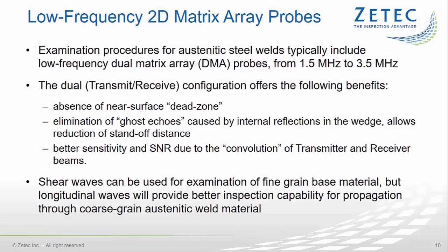Examination procedures for austenitic steel welds typically include low-frequency dual matrix array probes, often called DMA probes, with frequencies from 1.5 to 3.5 MHz. The dual transmit-receive configuration offers the following benefits. First of all, there is no near-surface dead zone. Also, there are no ghost echoes caused by internal reflections in the wedge. This means that the wedges don't require any dampening material on the front, so they can be made shorter. And as a result, the exit point of the probe can be positioned closer to the weld. This will allow for better coverage in the first half skip.